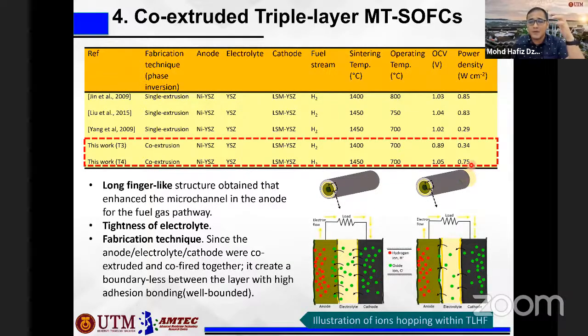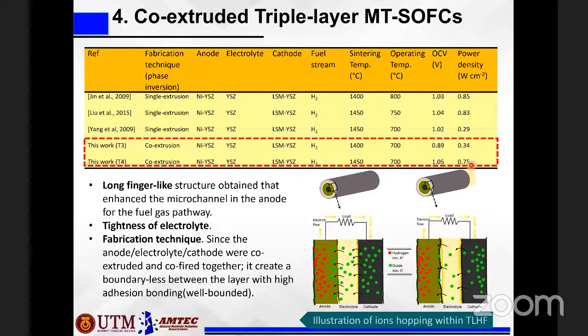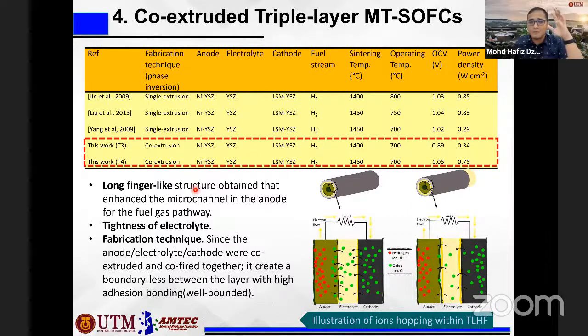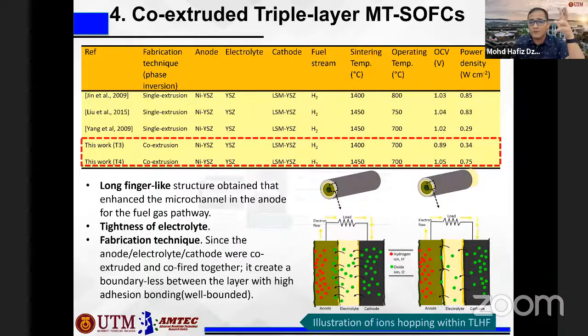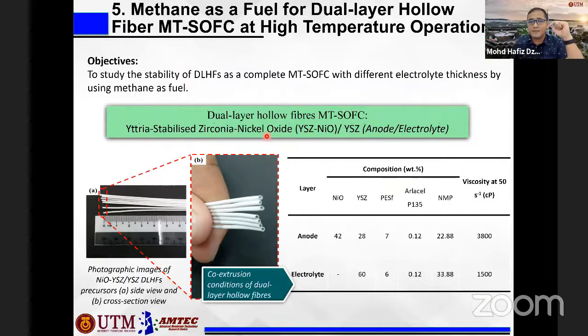Why is this? When we produce by using the phase inversion co-extrusion process, we can produce a tight electrolyte, and we also have a very seamless, boundaryless layer between the anode, electrolyte and cathode. Therefore, when the oxygen ions or electrons want to jump from one side to the other, they don't have any resistance because they can jump very smoothly. Lastly, we tried to use the dual layer hollow fiber membrane with different electrolyte thickness, and we tested with methane as the fuel.